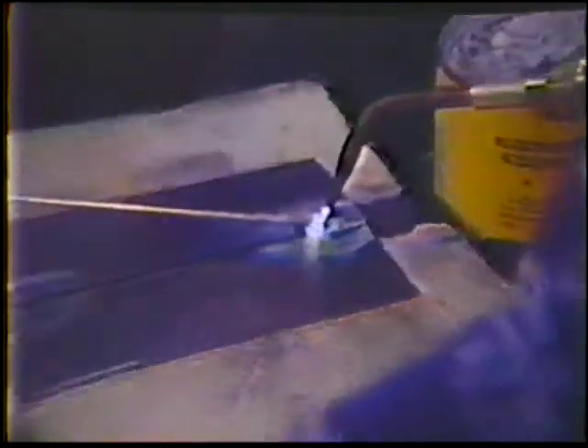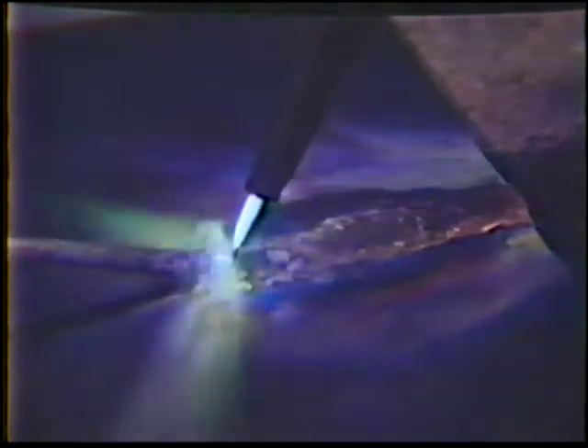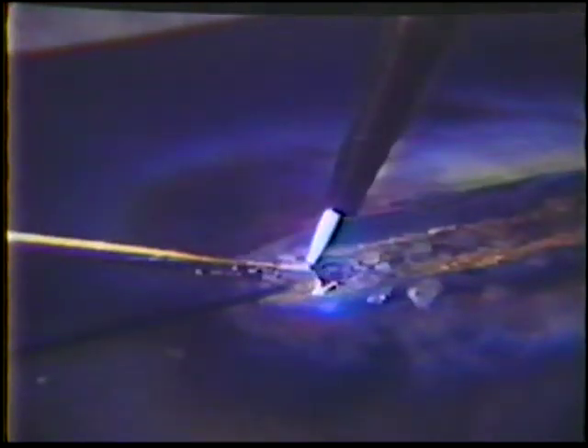When the metal becomes dull red, touch the rod to the spot to melt a little flux and filler metal, and continue heating until the metal is hot enough to melt the filler metal when touched to the area. Then move along the joint, adding filler metal as needed to fill the groove and leave a little reinforcement on the top. When the filler rod melts down to where there is little flux left, dip the rod in flux to replenish the supply. When the braze weld is complete, remove the flux on both sides with a wire brush.